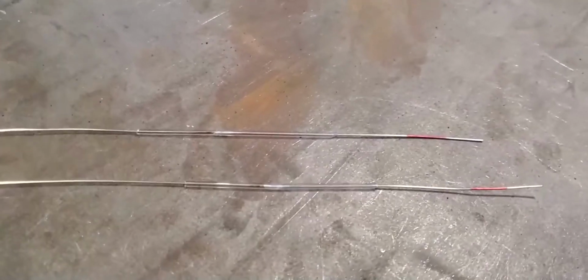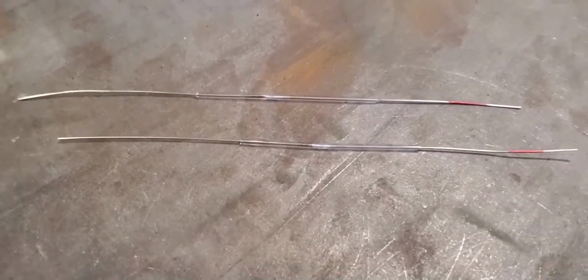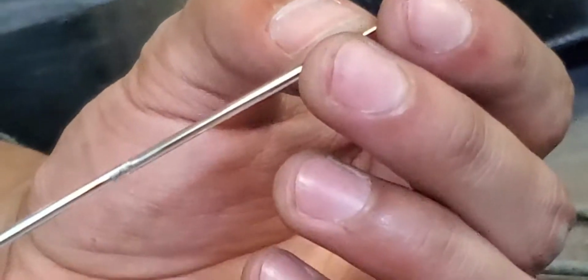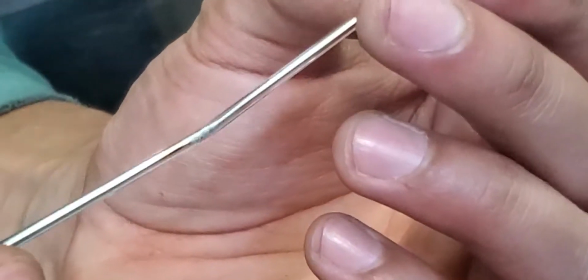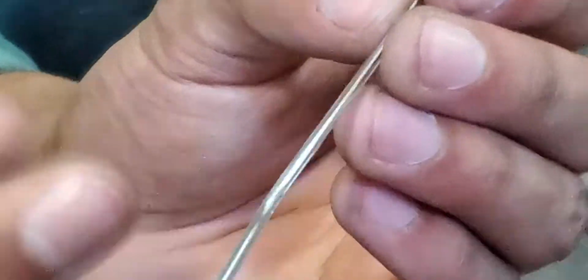And I'd also just tug on it. Right here. Just tug on it, make sure it's not going to fall apart. It's also a really good one. Also just check for like pits at the junction, or if you see green spots like chromium oxide, it might be bad. Or if there's a lot of black, like an oxide buildup at the junction, it might be bad as well. So those ones I usually just discard and break the quartz, snip the ends off the wire, and then just repeat the process.